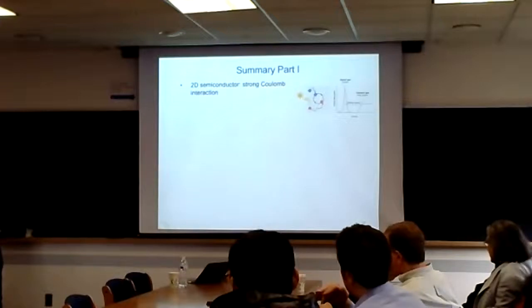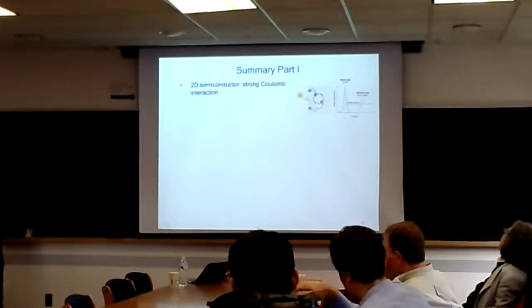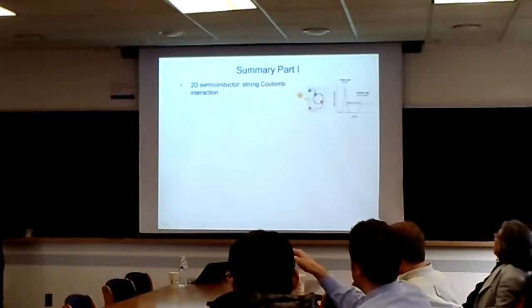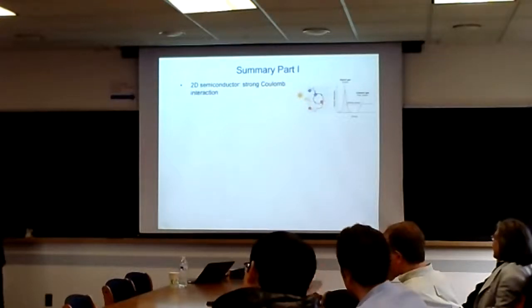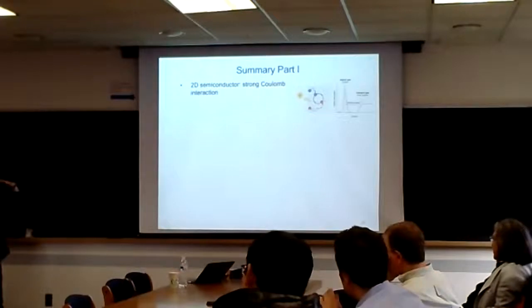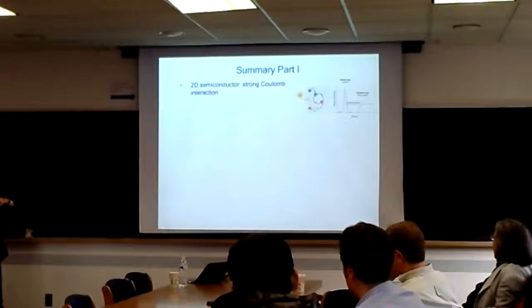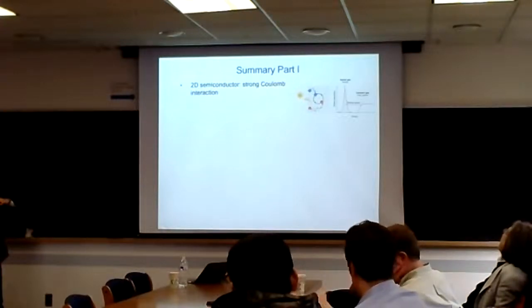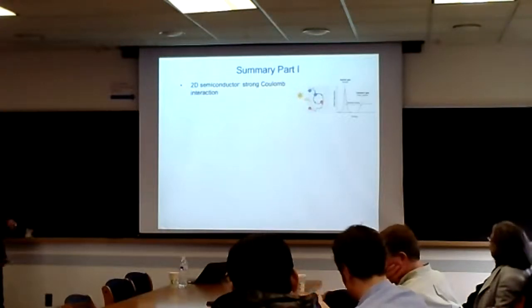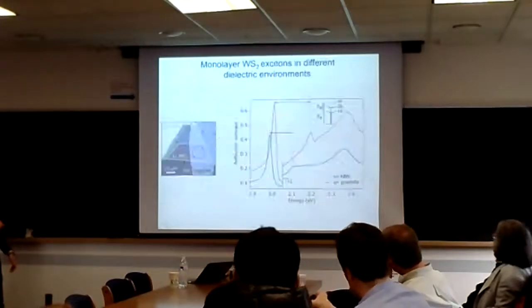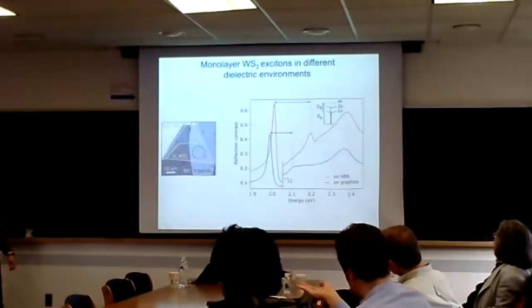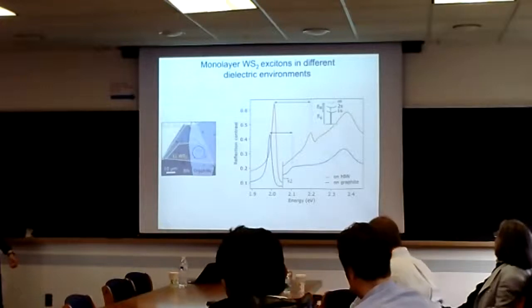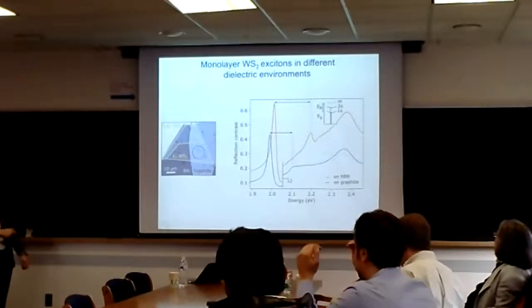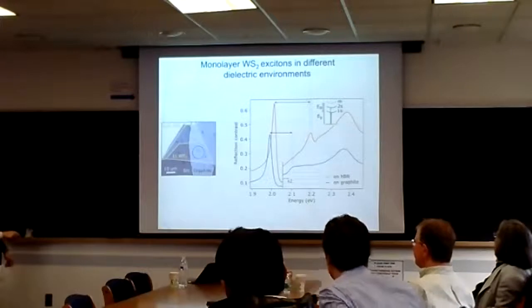I understand, but as you change the number of layers and the caps and so on, isn't it that the charging is going to depend? I don't mean to imply that the data is not right, I'm just wondering. So there's no cap on top, right? When you compare the pristine sample to a sample in which you've engineered the environment, doesn't the charging of either one of the two samples change subtly, and hence you have a rigid shift of the work function here?